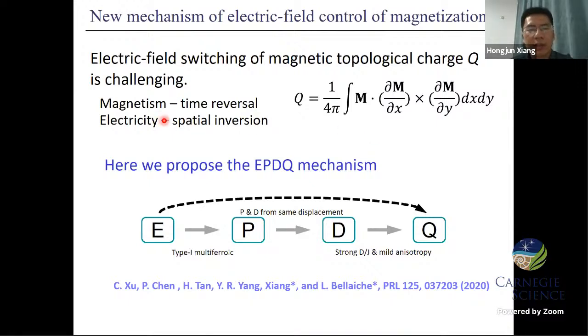So this is the magnetization and the magnetization derivative with respect to x and with respect to y. This is the integral of this. But we know that magnetism breaks time reversal, while the electric field only breaks spatial inversion. So how can we control the topological charge using the electric field? This seems very difficult. But fortunately, we found that there may exist a new mechanism we call the EPDQ mechanism. We can manipulate the sign of the topological charge.